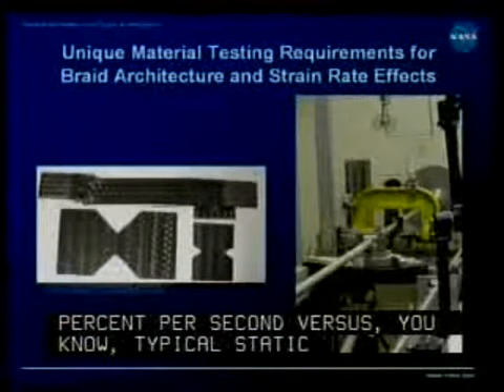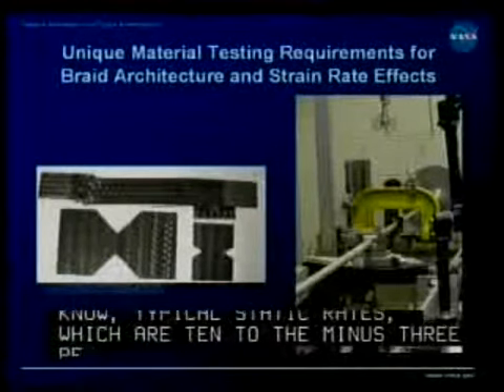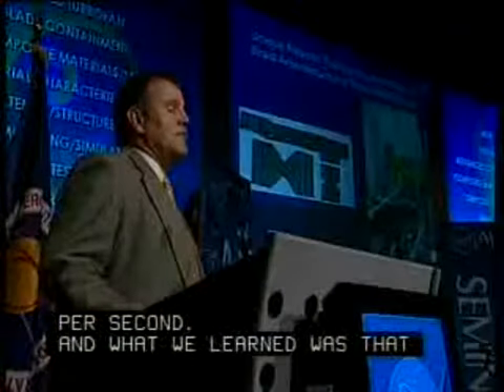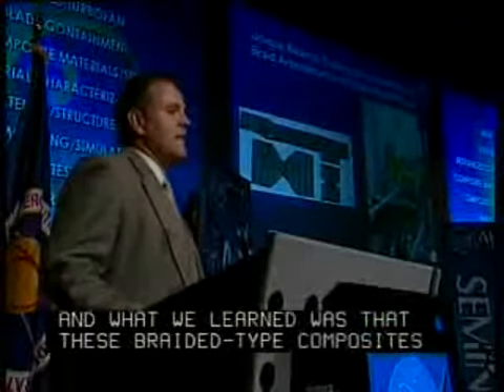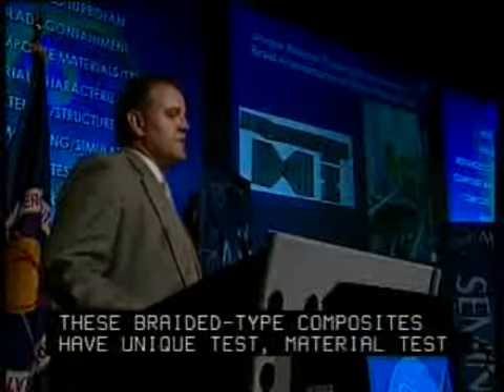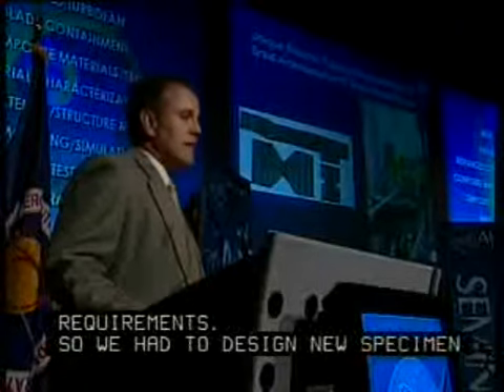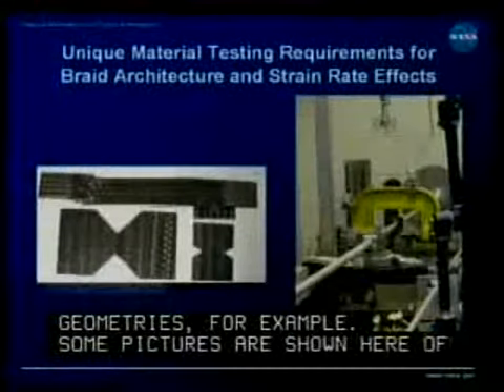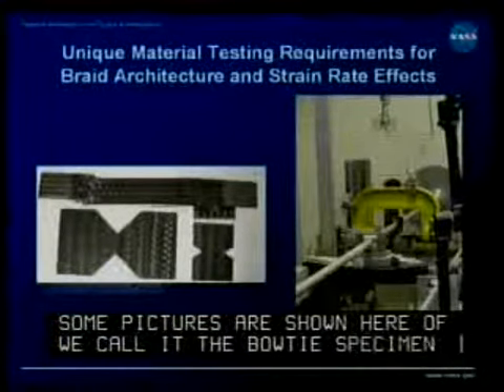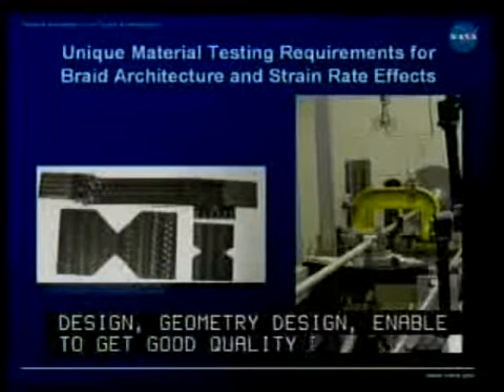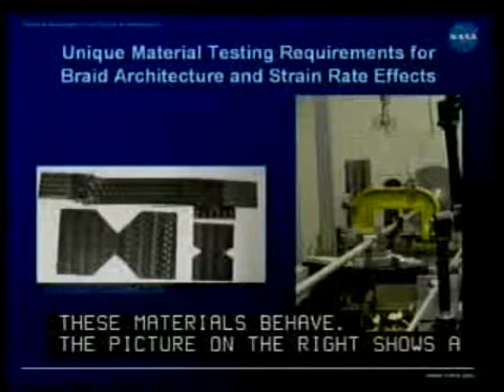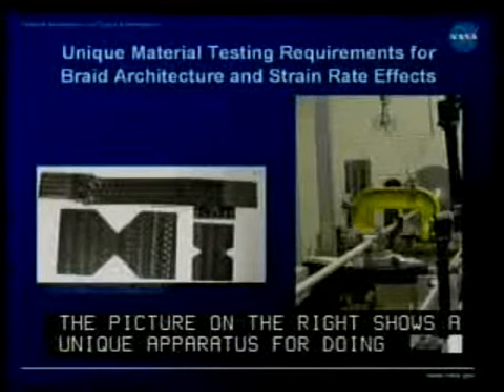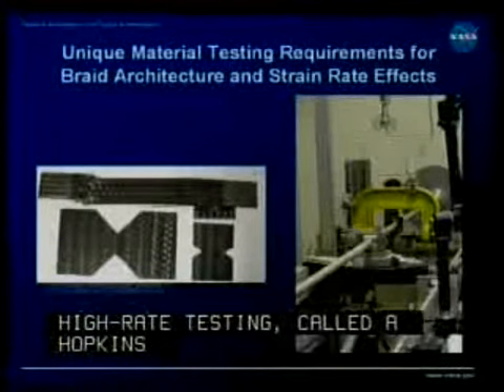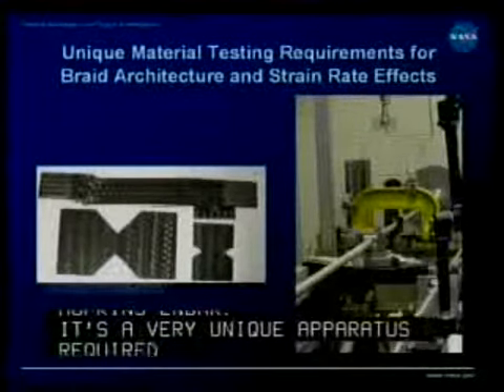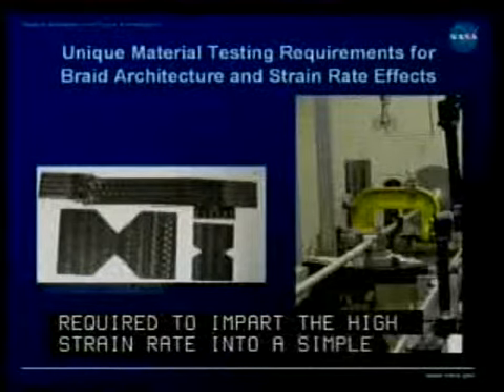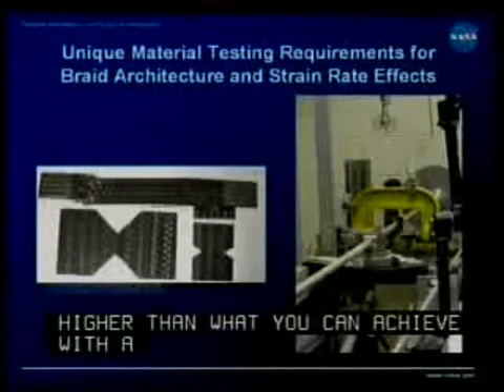And what we learned was that these braided type composites have unique material test requirements. So we had to design new specimen geometries, for example. Some pictures are shown here of what we call the bow tie specimen geometry design, and we're able to get good quality data on how these materials behave. The picture on the right shows a unique apparatus for doing high rate testing called a Hopkinson bar. It's a very unique apparatus required to impart a high strain rate into a simple material test specimen, higher than what you can achieve with a typical servo-hydraulic load frame, for example. Next slide, please.